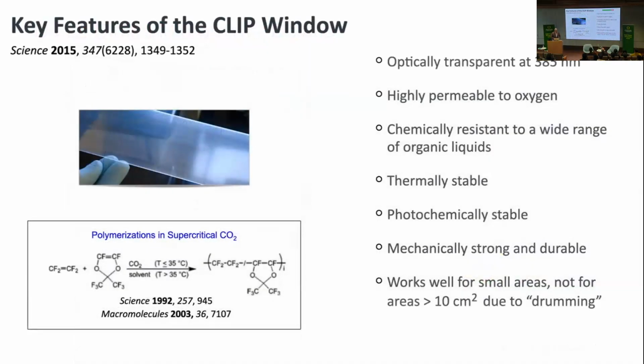The window is a very special window. It is optically transparent, but also allows oxygen to come through. And this is a class of fluoropolymers that we started working on a long time ago. It's an amorphous form of Teflon. And so it's optically transparent, but it's among the most oxygen permeable materials known.